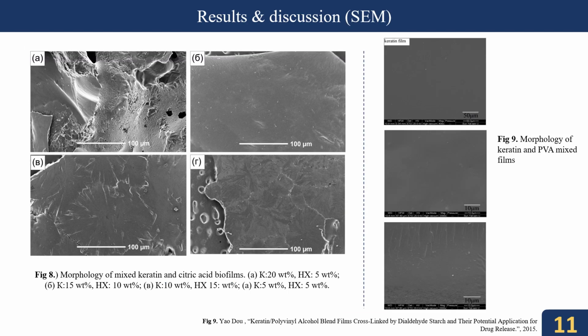Then we checked the biofilms using a scanning electron microscope. In this result, the ideal biofilm formation ratio was 15% keratin and 10% citric acid content. In this condition, the formed biofilm morphology was uniform, while at the highest keratin content the biofilm morphology was irregular or contained undissolved keratin. On the other hand, the sample with high citric acid content and less keratin content had an irregular morphology.